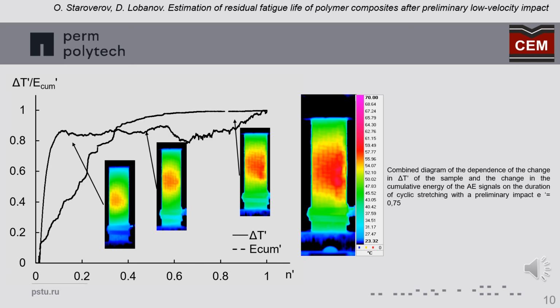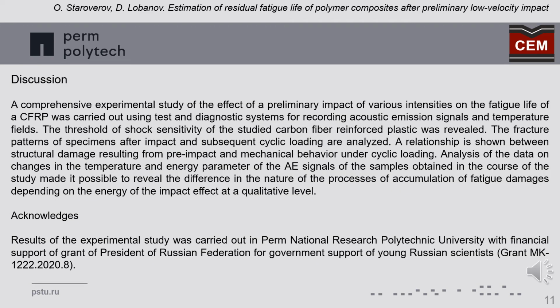Preliminary shock with energies in the range from 0.75 to 0.90 led to significant heating at the stage of the first cycles. A localized increase in the temperature was observed in the impact zone. A complex experimental study of the effects of preliminary impacts of various intensities on the fatigue life of structural carbon fiber composites was carried out using test and diagnostic systems for recording acoustic emission signals and temperature fields.